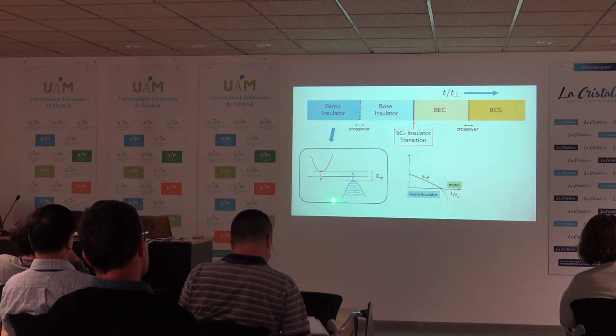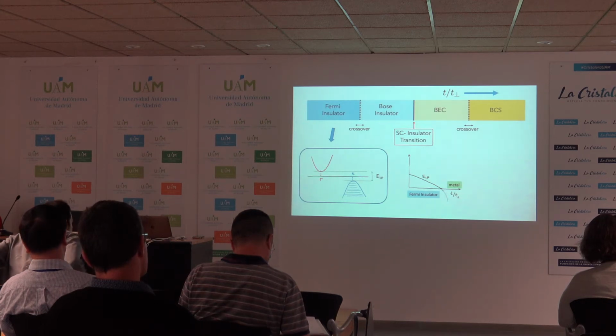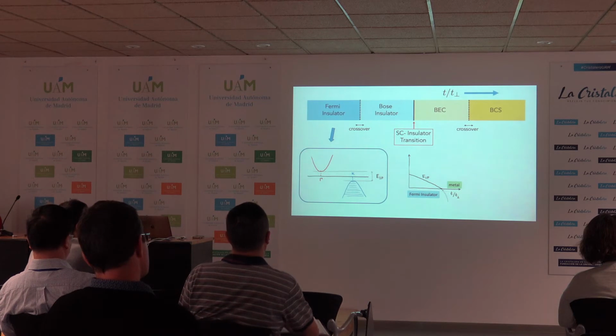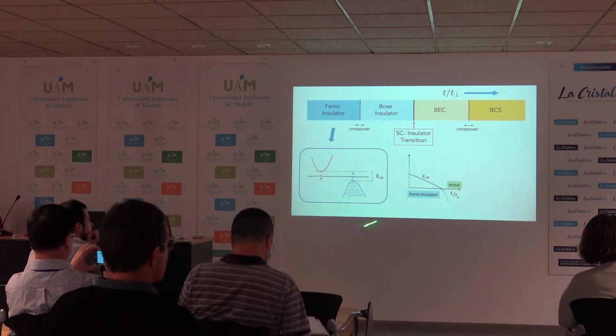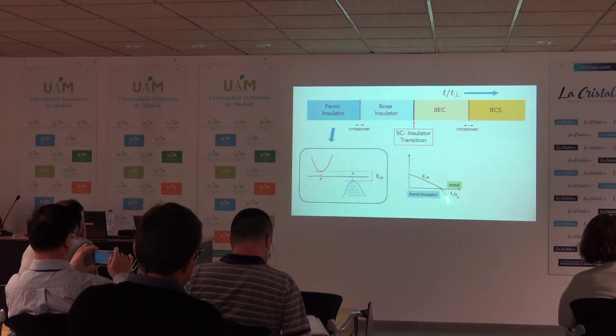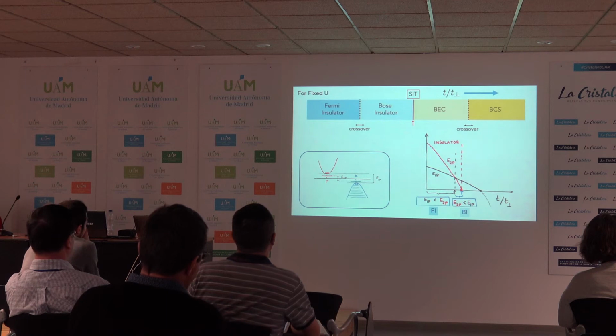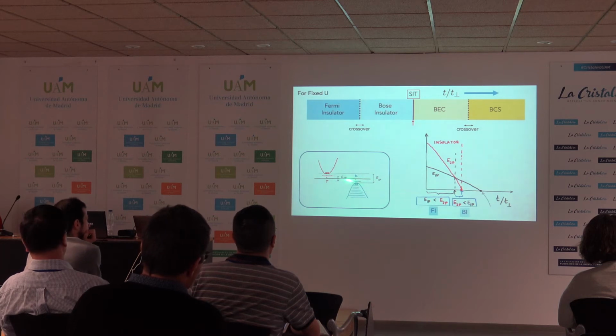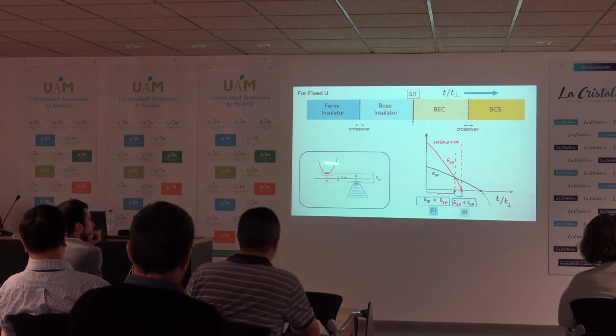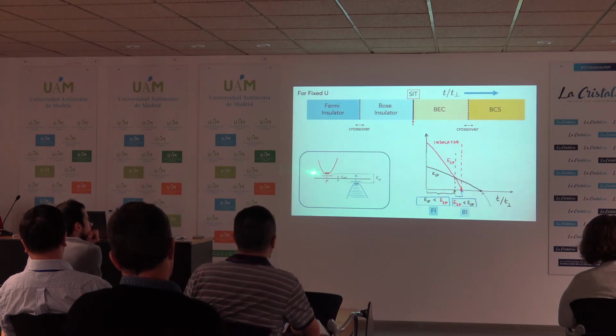So here is the Fermi insulator with a valence band and a conduction band and a gap. This is the single particle gap. So this is at zero attraction, so as you increase the hopping, the bands are going to get wider. At some point they will overlap and the single particle gap will close and make a transition into a metal. Now if there is a finite attraction, then what you find is that you can make a pair of holes within the valence band and a pair of electrons in the conduction band, and there is a two-particle gap that can still be finite within this region here.